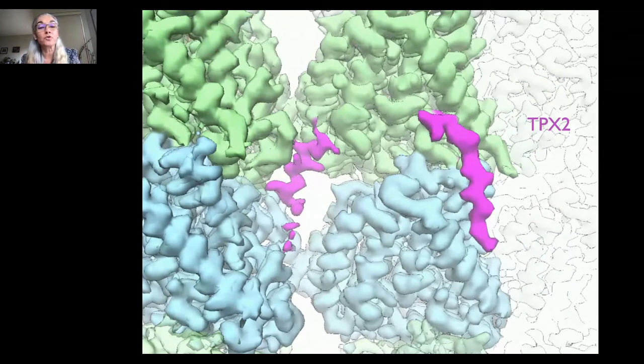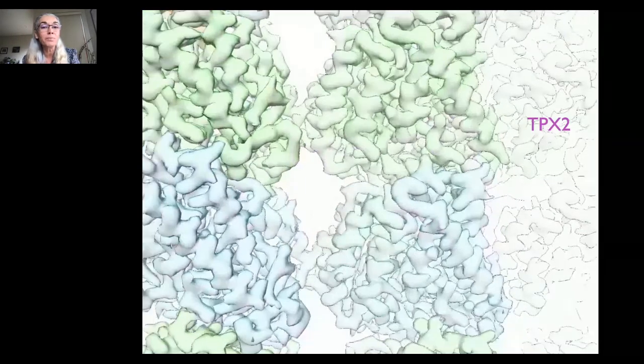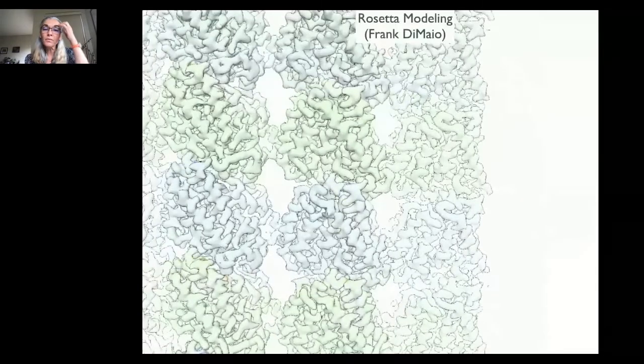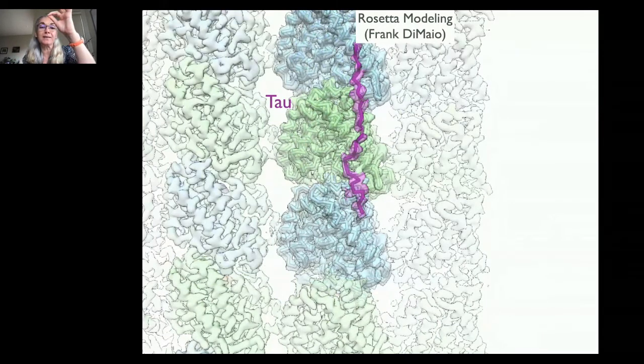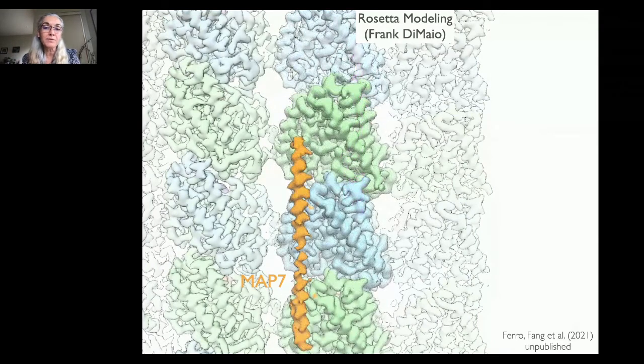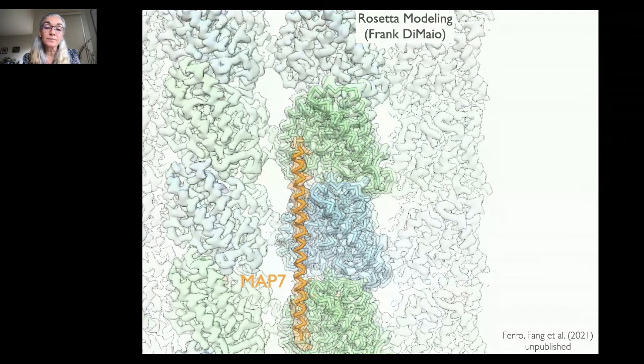There are others, however, that bind to the microtubule in an extended state, in some cases using parts of the protein that are unstructured and become stabilized only upon binding to the microtubule. And we can generate atomic models now completely de novo of how they interact with the microtubules. That was the case for TPX2. When it came to something like tau, which binds as an extended coil on the microtubule surface, we use tricks that I won't have time to tell you in detail, but maybe at the table, that combine Rosetta modeling with the constraints of the EM map to get to atomic models that minimize the energy of the molecule. And that has been very useful for tau, which we published a few years ago, and more recently for something not yet published, that is MAP7, a MAP that is very important in the regulation of motor activity that recruits and affects the binding of kinesin-1 in microtubules.